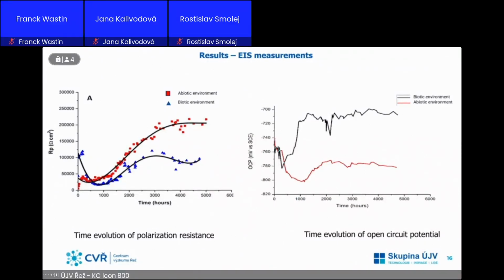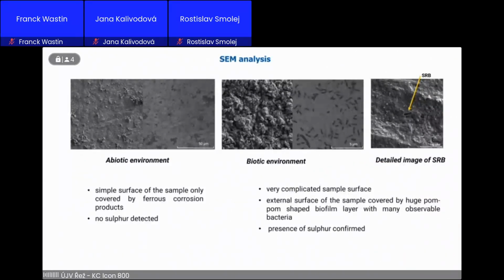This indicates that this corrosion rate is not destructive as biofilm that is under aerobic condition. SEM analysis shows that the abiotic environment was a very simple surface. The surface was covered only by ferrous corrosion products. We don't detect any sulfur. In the case of biotic environment, you can see a very complicated surface, pom-pom shape with many bacteria from the second layer of biofilm. And it was also confirmed the presence of sulfur.